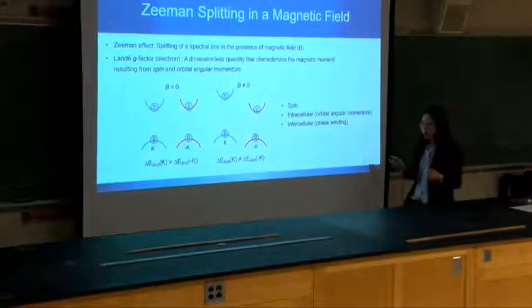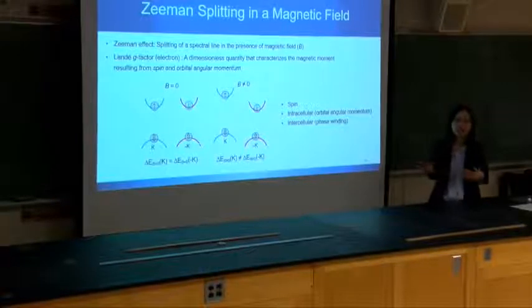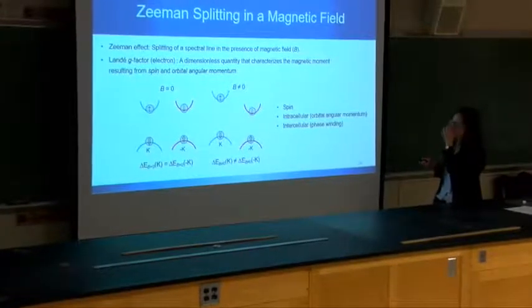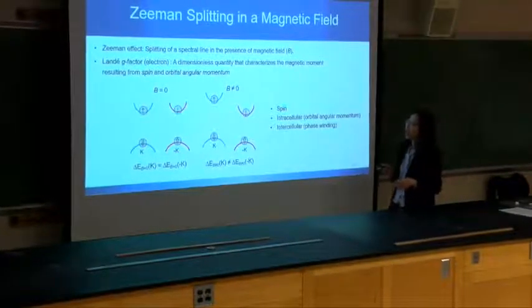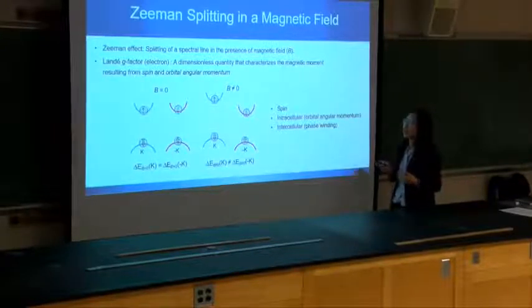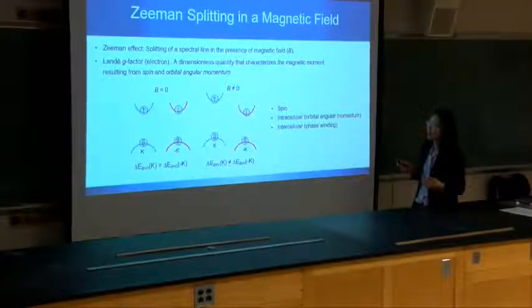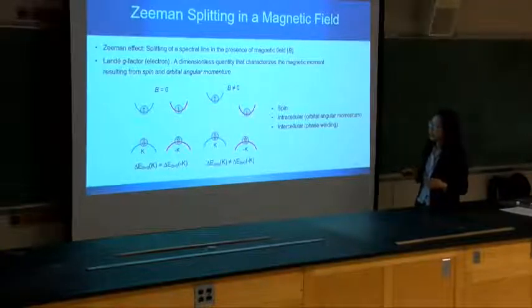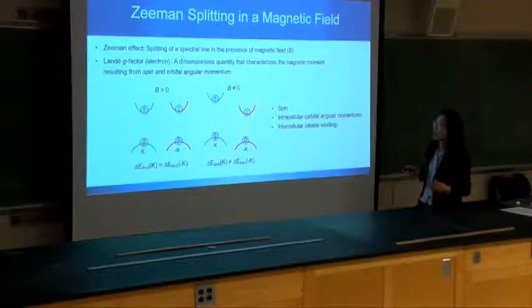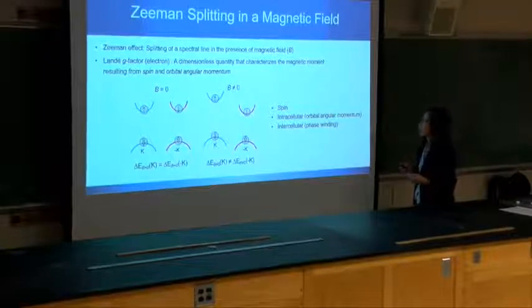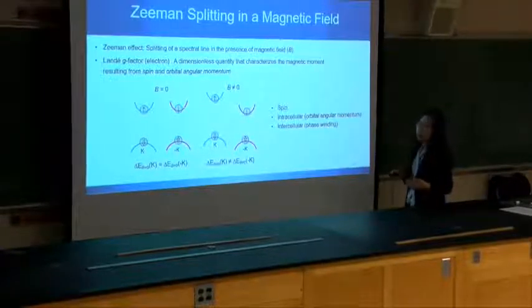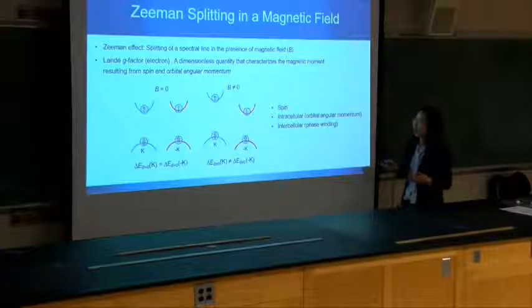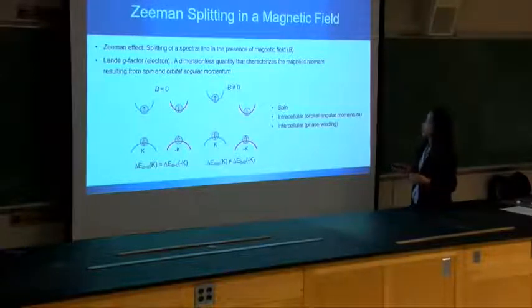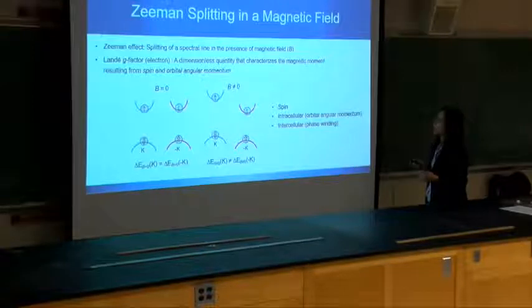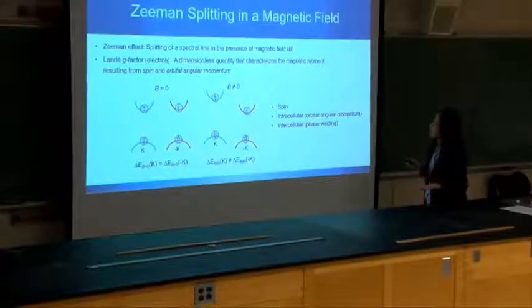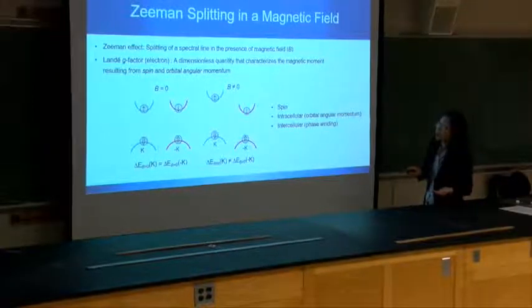The next thing we are going to explore is to apply a magnetic field to the sample to observe the Zeeman effect. The Zeeman effect refers to the splitting of spectral lines in the presence of a magnetic field. In this material system, there are usually three contributions. For spin, if we are observing the bright exciton, the spin will not contribute. And there's an intracellular contribution to the g factor that is related to the band character.